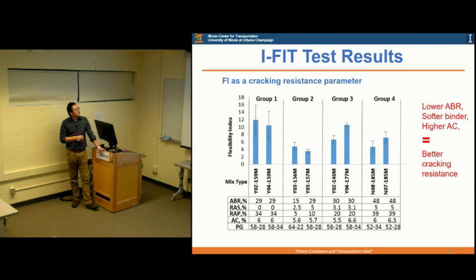Also I-FIT test results, this is the FI. We can see similar findings as the overlay tester. So you have the softer binder and also higher AC content for group 3, so you get a better cracking resistance.